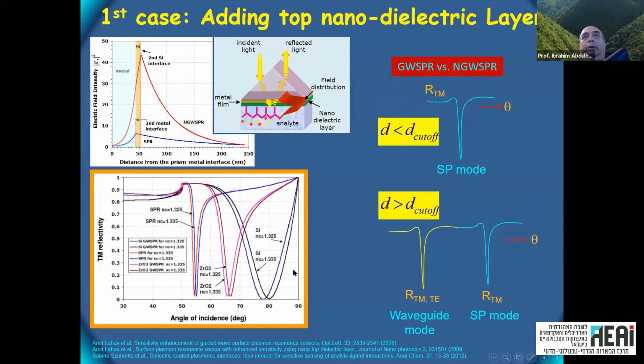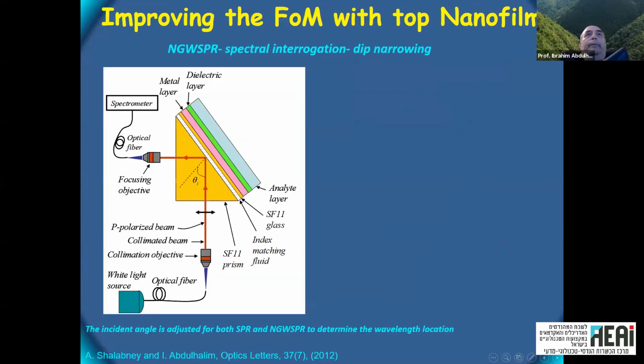And you can see here how the sensitivity increases as you change the refractive index of the medium. The shift becomes larger than the case where you don't have this additional layer. And the sensitivity also increases as you increase the refractive index of this top layer, which is why we use silicon, because it has higher refractive index.